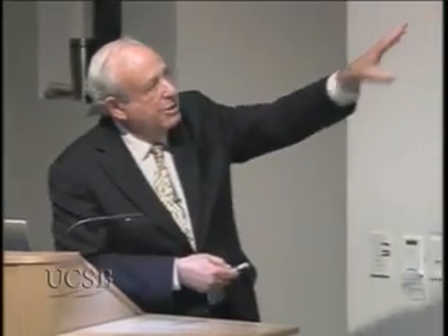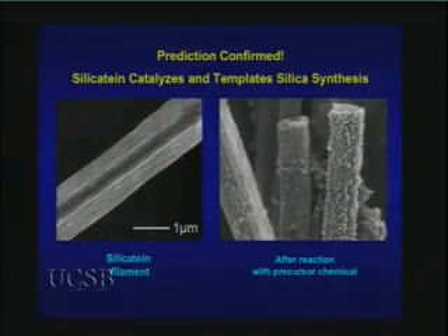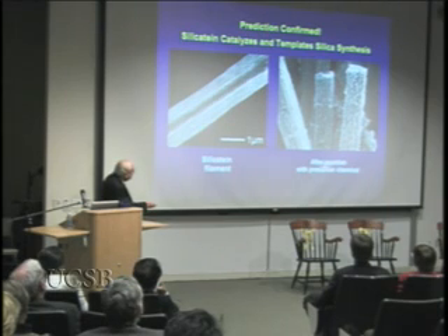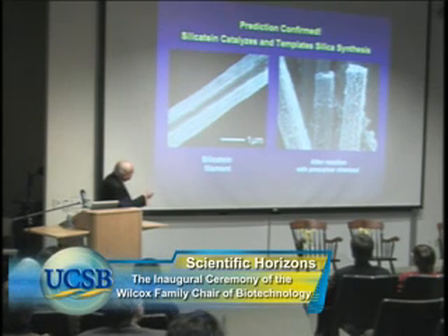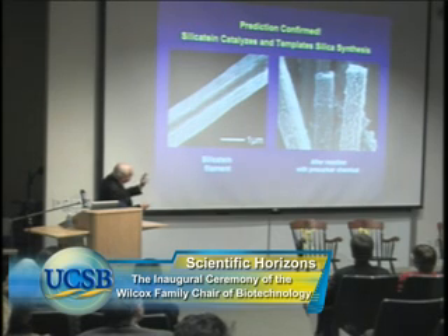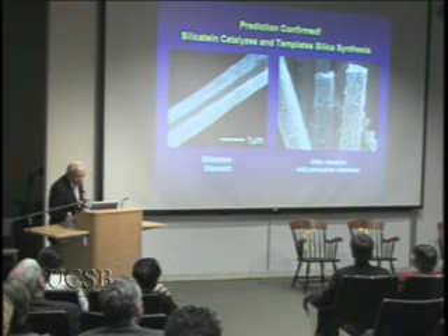If you strip away the glass from the protein filament, this is a high-resolution electron micrograph, there's considerable structure to this I don't have time to discuss, but we found that, sure enough, the surface of that protein filament is catalytically active. If we expose it to molecular precursor that can be hydrolyzed, chemically converted first to an intermediate and then condensed to form glass or silica, sure enough, at neutral pH and low temperature, the molecular precursor is converted to glass nanoparticles which bind to the protein filament. There are two activities here. The protein is active as a catalyst and also a template guiding the deposition of the newly formed glass.